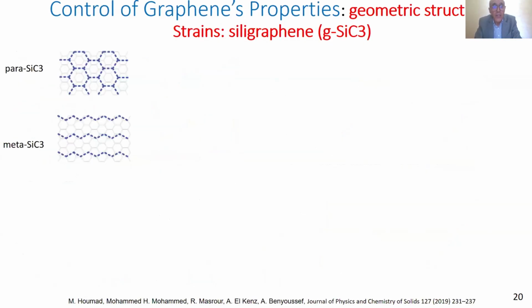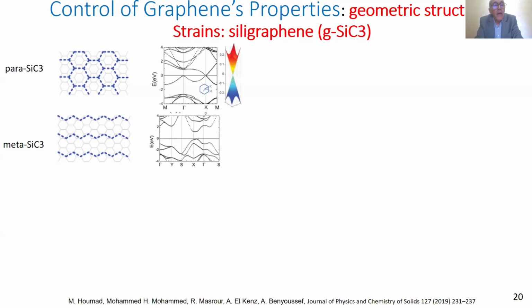So the properties of the material can change by changing the geometry of the same material with the same concentration. Here is another case of that, obtained with 25% silicon in graphene, and depending on the position of the silicon in the structure, we can have para-silicon carbide or meta-silicon carbide. The first one is semi-metal, while the second one is semiconductor.